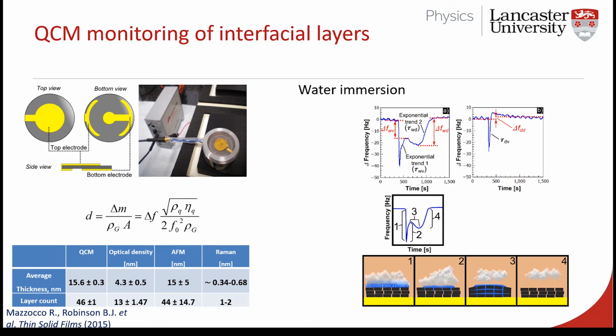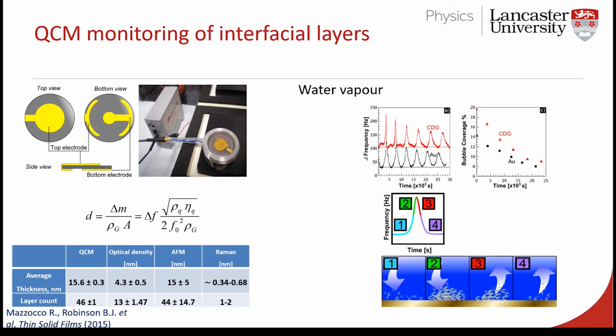But there was swelling of the material going on. There was water ingress into the structure. Using the QCM, we were able to monitor that and actually quantify the depth penetration of the water through the film, to the extent that we were able to influence the manufacturing process with how thick the barrier coatings had to be for these subsea applications. And we can do the same with water vapor. So if you're working in an environment which is very moist, not immersed, but very moist, again, we can tell a lot of information about how the moisture, how liquid content is binding to samples and how it's affecting them.